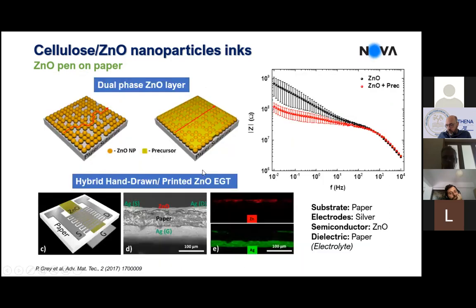We also developed in this ink a kind of mixture with a precursor. So you have zinc oxide nanoparticles, and in the ink we have a zinc oxide precursor. When you write this ink, you need to heat up to 80 degrees, which is compatible with paper, to decompose this precursor to form also an amorphous zinc oxide layer in between the zinc oxide nanoparticles that exist already in the ink. So the crystalline particles exist already in the ink.